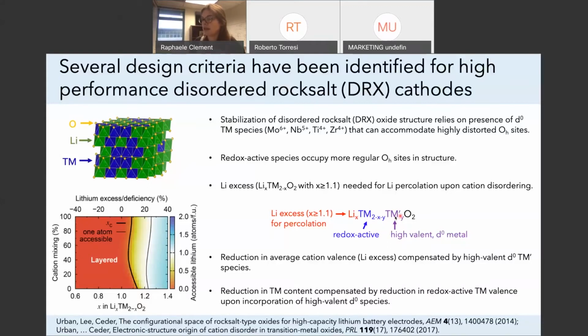This high valent cation also has a second use here, which is that by having more high valent transition metals, we can reduce the oxidation state of our redox active species, which means that we can increase the redox reservoir, the transition metal redox reservoir of our material.